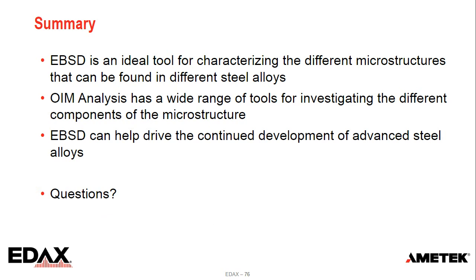It's a wide range of things we can use EBSD for on different steel applications. EBSD is really an ideal tool for characterizing a lot of these different microstructural features: the grain boundaries, the phases, the local misorientations, the orientation. And in the OIM Analysis software, there's a lot of tools built in. We can create a first-level map, we can do interactive analysis, we can do partitioning, we can do texture analysis. That really allows us to look at these in different ways and extract out information that's important, and really can help drive the continued development of these advanced steel alloys.